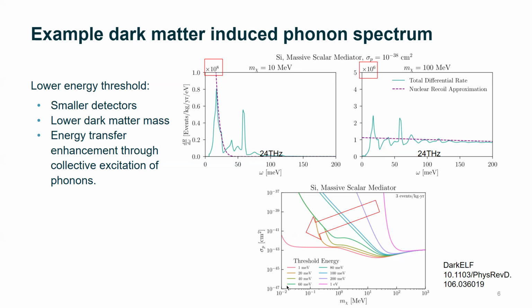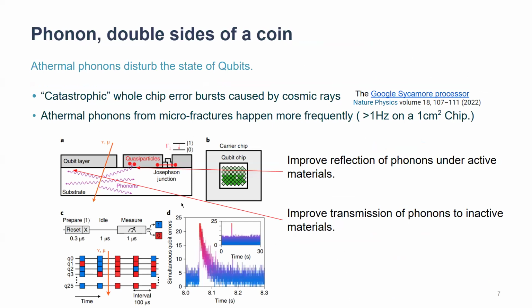So that's all combined together. You can look at this plot. This is a nice demonstration. If you go from 1 eV threshold to 1 milli-eV threshold, you can gain a huge amount of phase space here. So that is very exciting, and this is why we are pushing for a low threshold detector. But on the other hand, if we are looking for phonons, of course, this is a double-edged sword. For us, this is a good signal. It's great. But for quantum people, this is a problem.